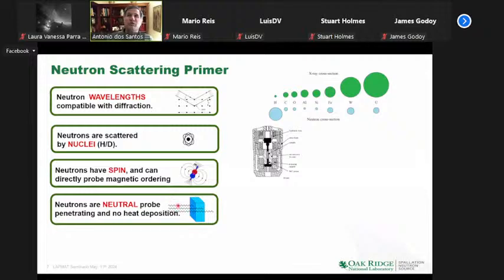Another thing is that neutrons are neutral. That has two implications. You can do a lot of engineering studies without having to cut through the pieces, which can lead to relaxation, so you don't really know what's there. Also, you can make really complicated sample environments to your heart's content, and neutrons can come in and can come out, and you can still get data from your sample, provided you have good alignment and good collimation.